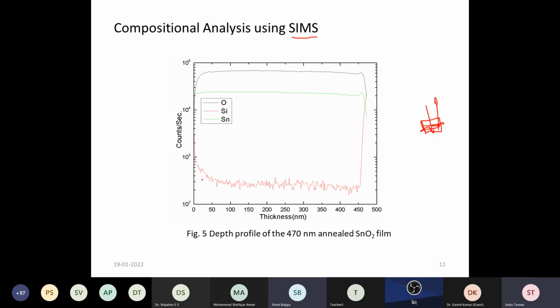And here we can see at the surface, the amount of silicon is not too much, while oxygen and tin are smooth across the thickness. When it reaches the substrate, suddenly silicon increases and tin and oxygen decrease. So this is known as secondary ion mass spectroscopy. In India, only a few places have this facility. One is NPL Delhi, I think, and another is IGCAR Kalpakkam. There we can determine how uniformly our film is deposited. That can be determined using SIMS, that is composition analysis using SIMS.